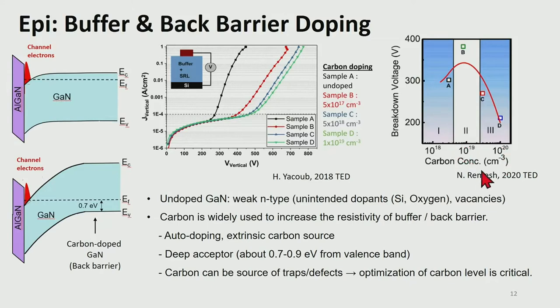Moreover, if the carbon level goes above a certain threshold, it can also flip the leakage versus the carbon trend. So if you see this right figure, up to about 1E19 per cubic centimeter, the increasing carbon is helpful for the breakdown voltage improvement. But if the carbon level goes above 1E19 or close to 1E20, now the trend is flipped and we start to see the degradation of the leakage current. So the carbon level optimization is one of the key design parameters for high-quality epi design.